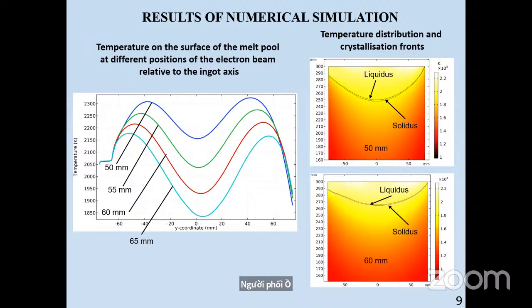As a result of the calculation, a graph of the temperature distribution on the surface of the liquid metal pool is presented. It was established that the power of the electron beam and its geometric position on the surface significantly affect the crystallization front and the temperature distribution in the ingot.